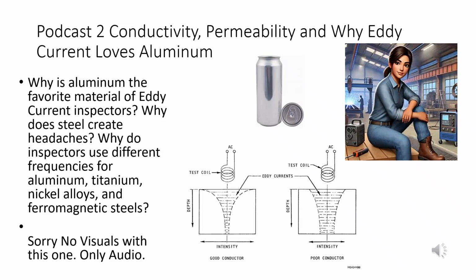Typical conductivity examples. Let's build some intuition. Copper is roughly 100% IACS. Aluminum alloys might be roughly 25 to 45% IACS. Titanium alloys may be around 1% IACS. Certain nickel alloys may be around 1 to 3% IACS. Think about that. Titanium may conduct electricity 30 times worse than aluminum. That becomes extremely important, and it's why aluminum behaves differently than titanium.